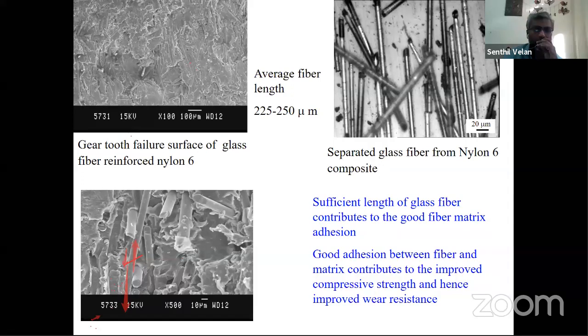Pullouts are not much happening, though you are able to see some fiber extruded. Not much pullout, not much hole you are able to see. Sufficiently, the fiber and matrix are in bond with each other. Good adhesion. This is separated fiber. Good adhesion is happening, so naturally, you will be able to see better wear performance, resistance, and so on.